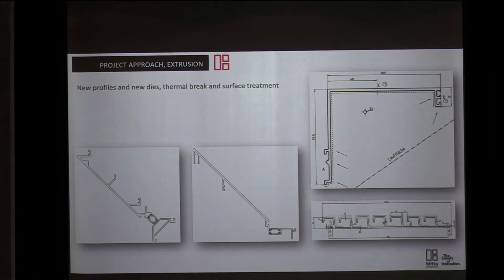These are also very hard profiles, not just for extrusion. For example, this one is a thermally broken profile, but the more this part comes out of the metal, the harder it is to make a thermal break. This one is the same, for the insulation part. This one is, for example, for the powder coating. When you powder coat an aluminium profile, the aluminium profile is positive and the polyester dust is negative. But when you put the polyester powder over here, it mostly goes there and there. Getting it in there is very difficult.